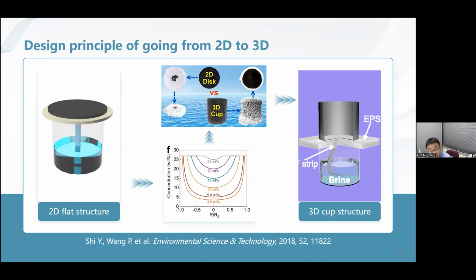All right, our idea was to produce a three-dimensional solar crystallizer, as I present here. Now, we think this design might work because when the brine is delivered to the center of the bottom of this three-dimensional structure, it will spread out, move towards the side, and then upward along the wall. With this design, the evaporation takes place only on the external surface of the wall. Therefore, there will be no salt accumulation inside of the cup. By this design, we physically separate the light absorption area from the salt accumulation area.